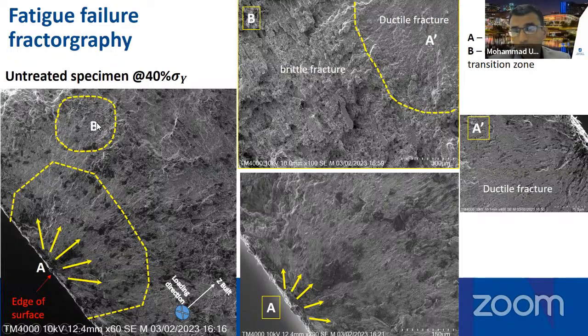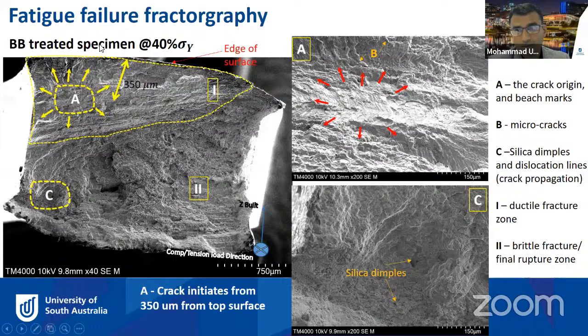However, we found that for the treated surface, after our ball burnishing treatment, the crack initiated not from the edge of the surface, but rather somewhere inside, around 350 microns deeper. That means after we applied the ball burnishing, we modified the subsurface microstructure, and that allows the crack to start a little bit from the subsurface, not from the edge of the surface. So this is another indication of the improvement of the fatigue life by the ball burnishing.